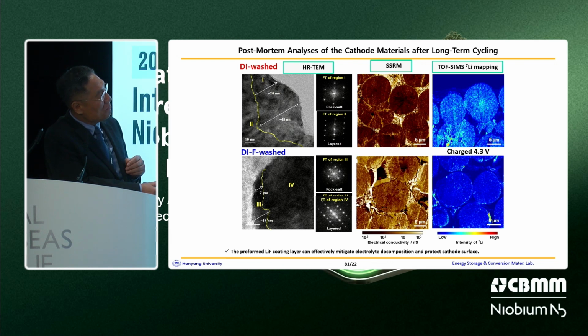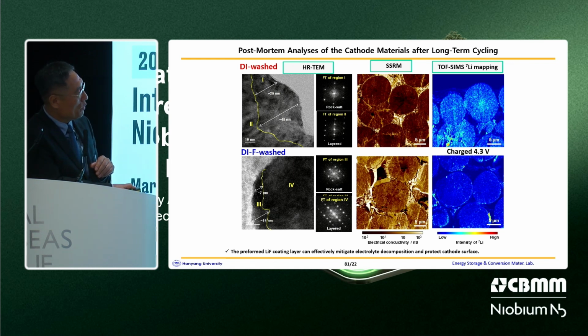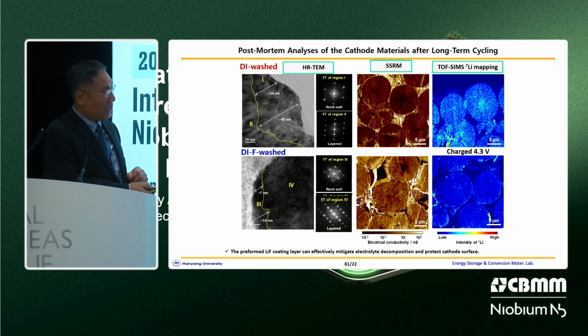And also, the SSRM image of the DIF-washed cathode shows that the entire particle is nearly electronically active, whereas that of the DI-washed cathode clearly shows nearly zero electronic conductivity. And as shown, ToF-SIMS 7Li mapping. This is a charged state, fully charged state. As you can see here, some 7Li was observed in the particle interior in the DI-washed cathode. However, in the case of the DIF-washed cathode, you can see no 7Li is observed throughout the particles. And again, I believe that the preformed LiF coating layer can effectively mitigate electrolyte decomposition and thus protect the cathode surface.